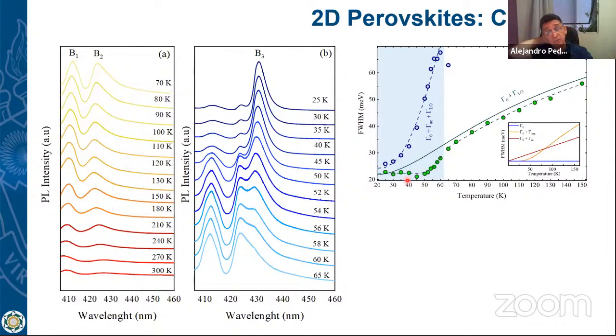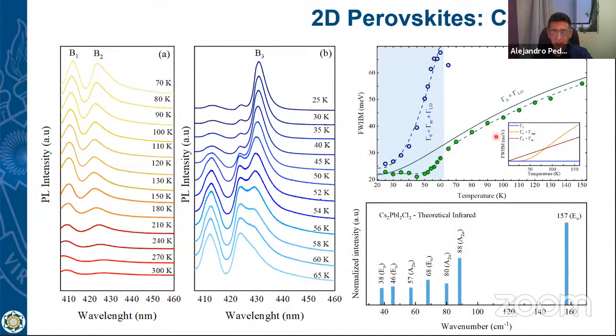But if you have an exciton-phonon coupling, the phonon involved could not be a Raman band, but it must be an infrared band. And from the fit, we calculate the band should be more or less at 150 wave numbers. And if we go to the quantum DFT calculation, we can see that in fact there is an infrared mode which we have around 150 wave numbers, and which is the one associated to the electron-phonon coupling.